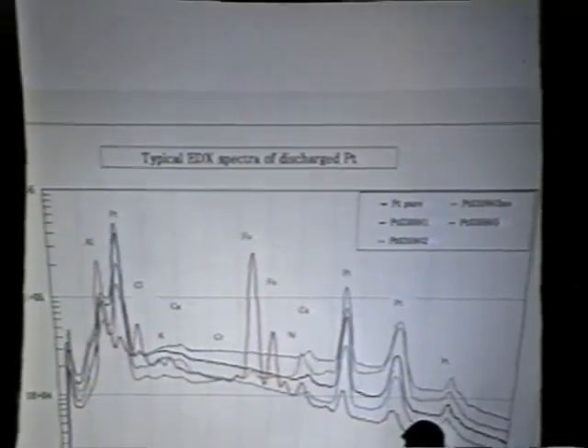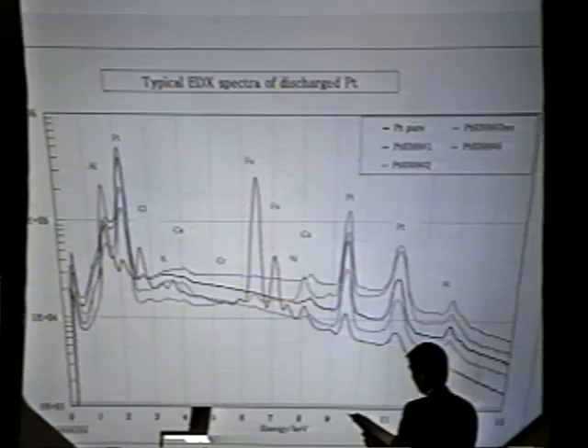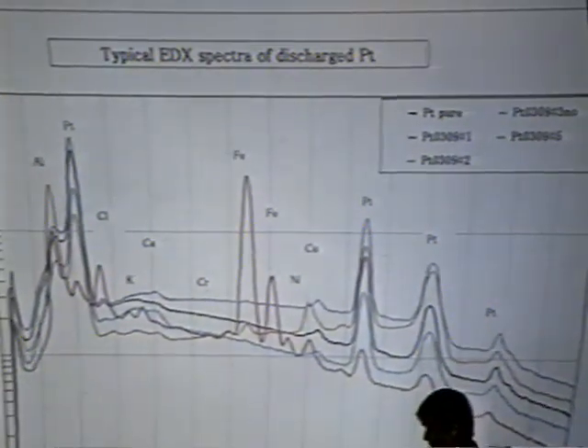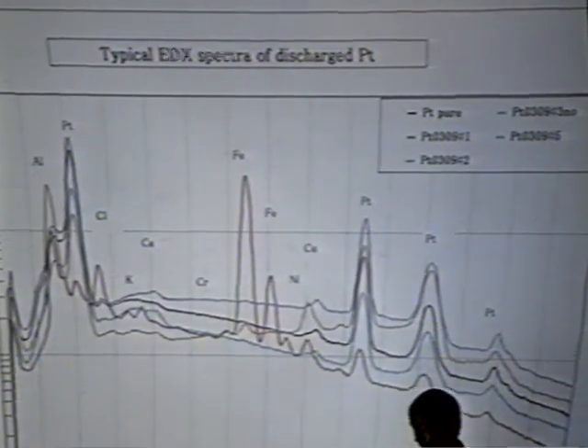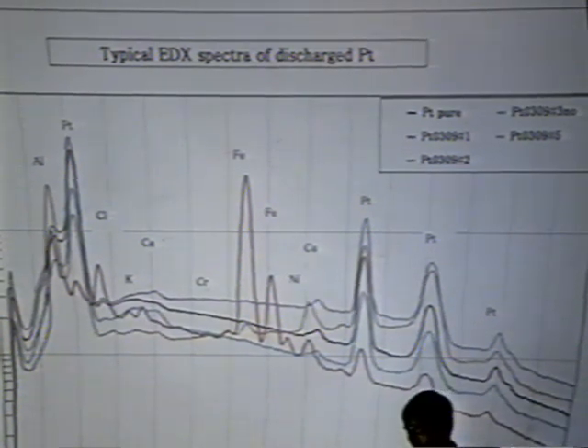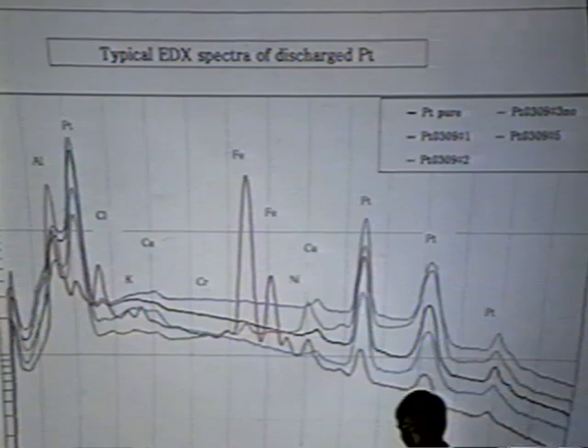This is a typical result of EDX measurement. You can see large iron, chlorine, nickel, chromium, potassium, and calcium peaks, alkaline carbonate materials. However, in each experiment, I can see such kinds of elements. The distribution and intrinsic elements were changed by electrolysis conditions. Thank you.